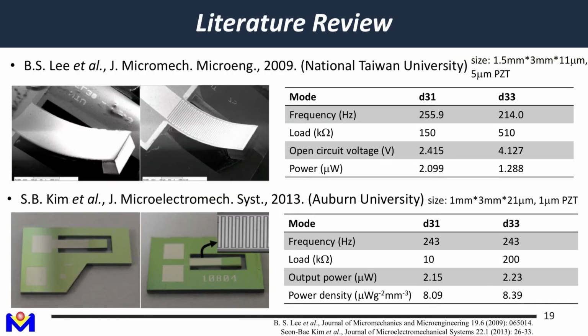Okay. So this is some study in 2009 and 2013. This is from my lab, and this is from Taiwan University. So you can see in our results, the 3-3 mode, this is a fair comparison, is actually a little bit worse than the 3-1 mode. And for the study from Taiwan University, the 3-3 mode is a little bit better than the 3-1 mode. So it actually does not follow the prediction. If we look at the piezoelectric constant alone, the 3-3 constant is about 1.5 to 2 times larger than the 3-1 piezoelectric constant. But if you fabricate a whole transducer, there are a lot of different perspectives you have to look at. Then it's not that easy. The total generated power is actually not higher compared to 3-1.